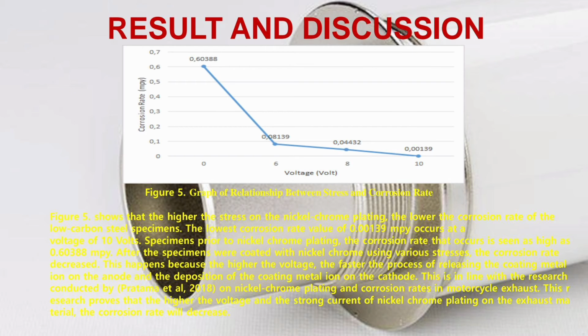Results and discussion. Figure 5 shows that the higher the stress on the nickel chrome plating, the lower the corrosion rate of the low carbon steel specimen. The lowest corrosion rate value of 0.00139 mpy occurs at a voltage of 10 volts. For the specimen prior to nickel chrome plating, the corrosion rate that occurs is seen as high as 0.60388 mpy. After the specimens were coated with nickel chrome using various stress, the corrosion rate decreased.